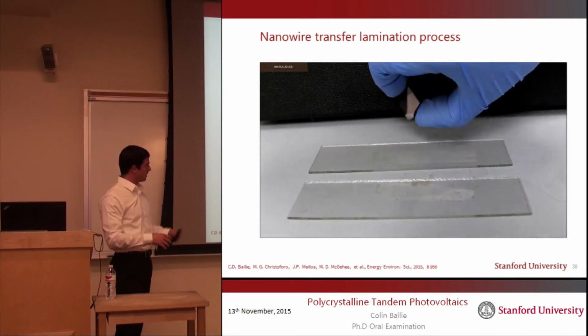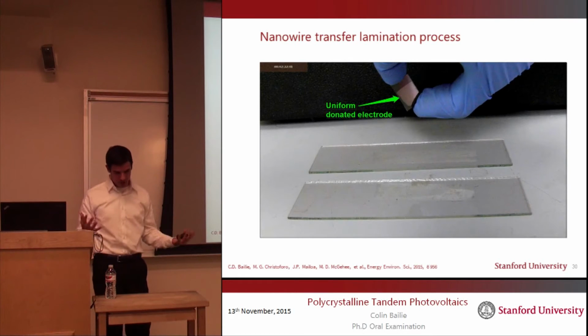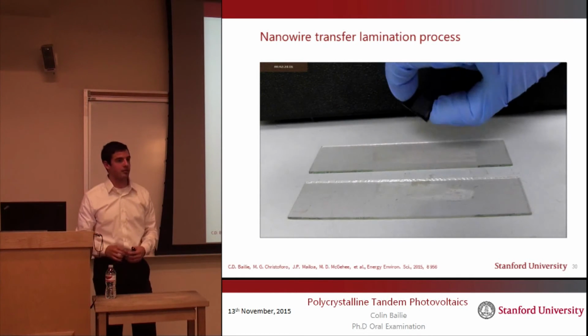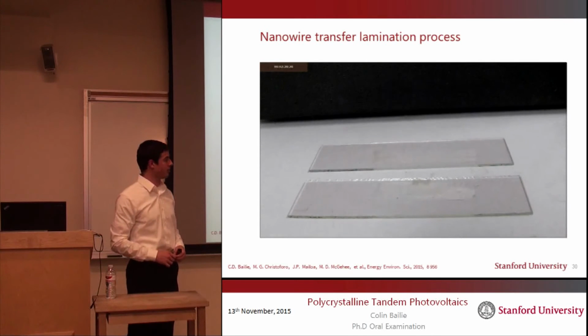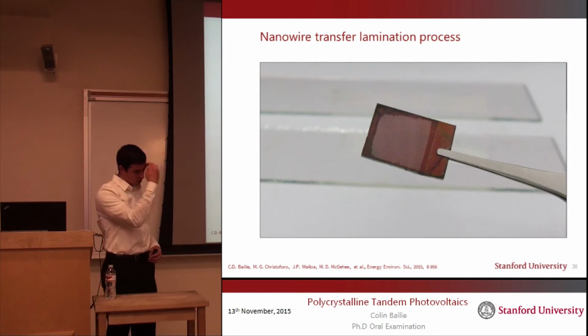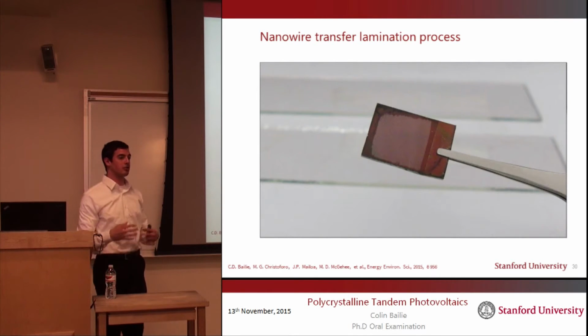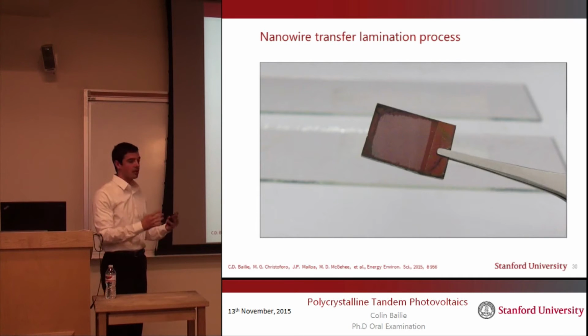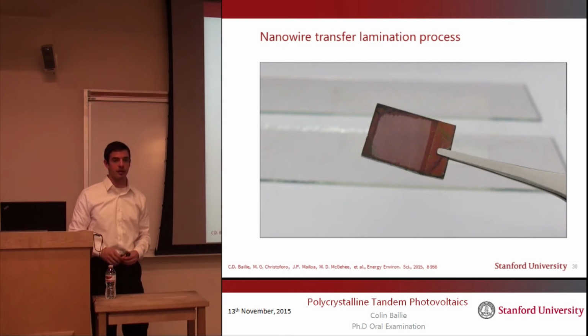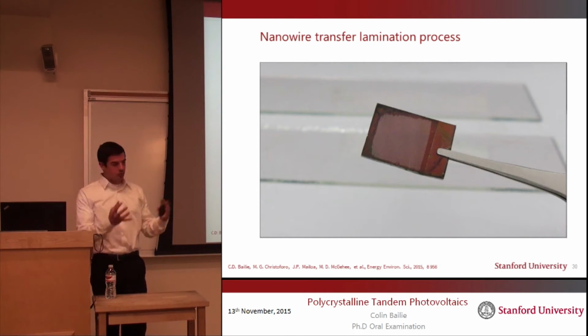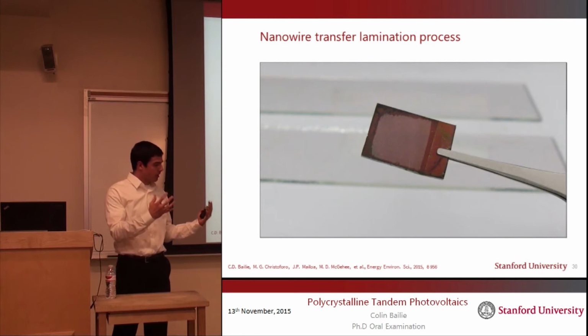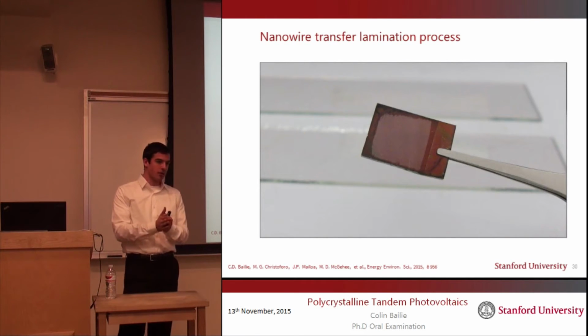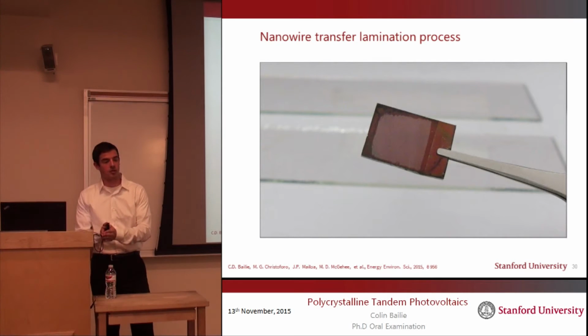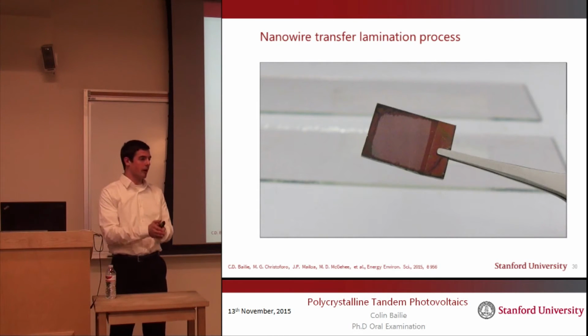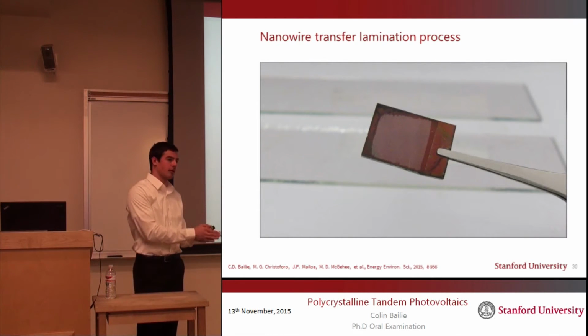And you'll see in a second, it doesn't look particularly transparent, and that's because these silver nanowires contribute some haze. But when you throw this into the spectrometer and measure what the transmission looks like, it's actually quite transparent in the infrared. So what we did here was to create a way to deposit a transparent electrode onto our perovskite solar cell that was compatible with the needs of the perovskite.